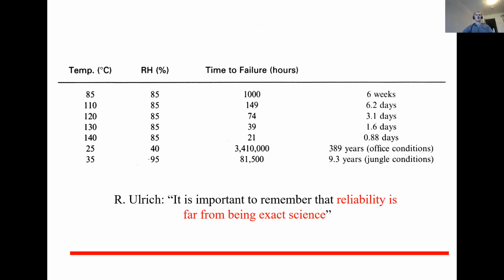So maybe to conclude, here is a table. Maybe you can now have some kind of picture in your head which roughly states these values. Here we start from the standard 85-85 test for 1,000 hours, which it says here is 6 weeks, but it's not 6 weeks. I don't know how they calculated. I think it's less than 5 weeks, but anyway, in that order of magnitude. And then if you start going to HAST testing, you increase the testing temperature and keep the relative humidity at 85, and the testing time goes from several weeks down to less than a day at 140 degrees.